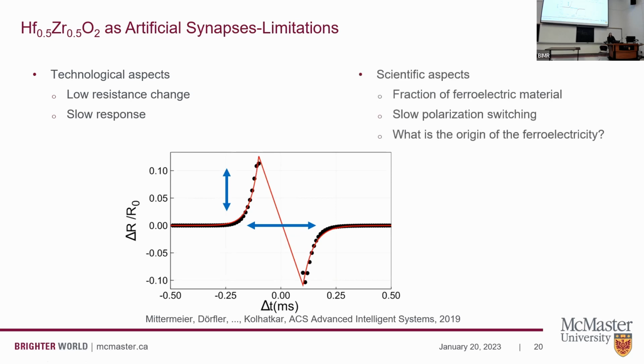And this is due to some scientific aspects. The first one, the resistance change, is due to a low fraction of the material in the ferroelectric phase. And the slow response is due to a slow switching of the polarization within the grains. And all of this could be improved by understanding the origin of the ferroelectricity in our devices.